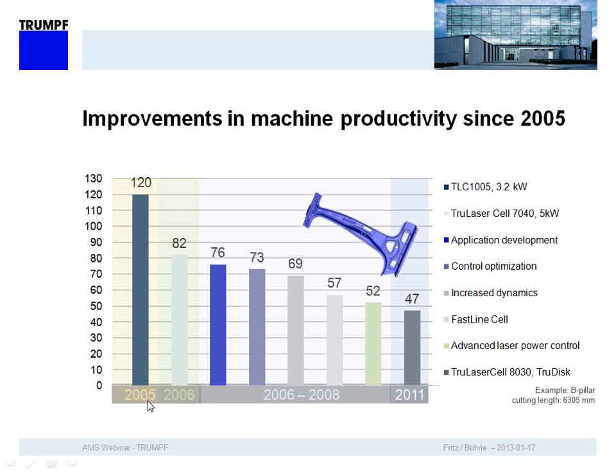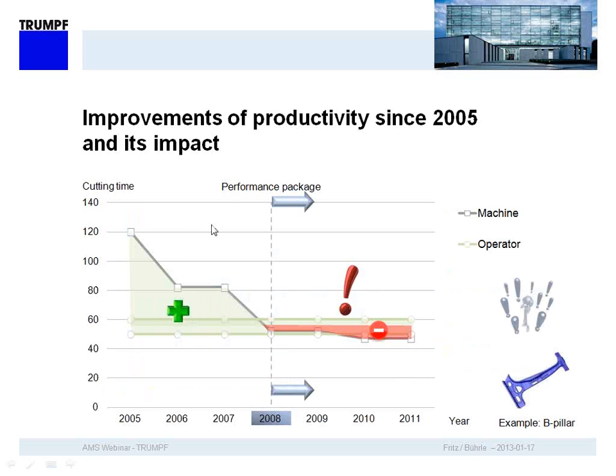Another thing that we have done for many years, down here you see the years 2005 to 2011, that's when we really started to cut those components in very high volumes. Back then we had a chance to get this part here. It's still our benchmark part. It's a B-pillar, actually of the Passat B6, and the cutting length is a little bit over 6 meters, and it has numerous holes in it. With our machine generation from back in 2005, it took us 120 seconds for completely processing the part. So with introducing new generations of machines, new laser technologies, and packages that increased the dynamics of the machine, we brought this cycle time down to nowadays about 47 seconds. So really shortened the cycle time a lot.